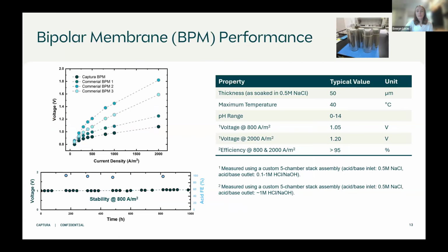So from these numbers, we're able to produce the plots you see here. So again, we scan a range of current densities and we measure the voltage across the bipolar membrane. Captura's bipolar membrane that's cast in this roll-to-roll fashion has been able to achieve excitingly low voltages. And when testing multiple other commercial membranes in our same system, we achieve the lowest voltages that we have observed.